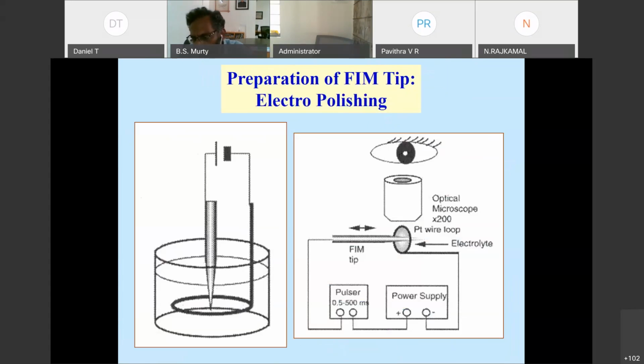But how do you prepare that kind of a needle is a very important thing. The needle should be as sharp as the diameter at the tip should be approximately around 50 nanometers or so. If you don't have, you will not have a field enough generated to pull an atom from the tip, because it's basically a field that you generate. If the field is large enough than the interatomic forces, an atom will be pulled out. So for that, you need a very sharp tip.